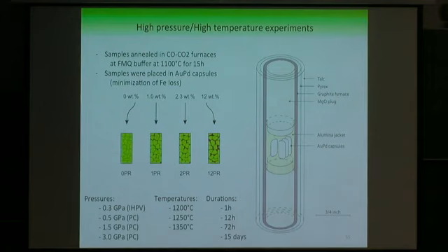And I would like to point out that the piston cylinder assembly used talc. And so this talc is known to diffuse hydrogen during the experiment and exchange its hydrogen with the iron, thus producing water inside the capsule. And that could create some problems, namely increasing the water content in the sample. And well, water has been shown to increase grain growth. So to check the water contents of the sample, as I will be showing later, I've performed FTIR measurements.